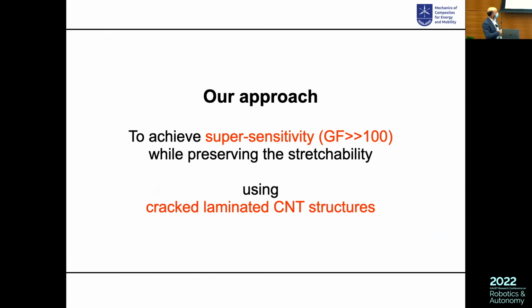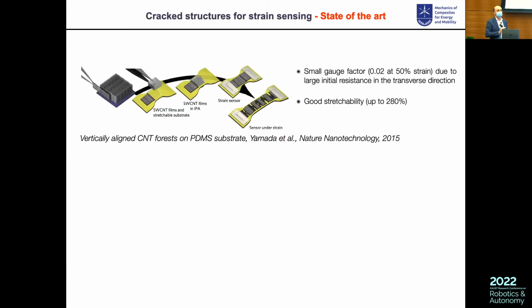So our approach to reach this super high sensitivity is to use, at the beginning, cracked films of CNT. We are going to use films of carbon nanotubes, and we are going to play with the piezo-resistivity of the cracks that you can introduce inside these films. Introducing cracks in a material to get piezo-resistivity is not something that is new. You have at least these two papers.